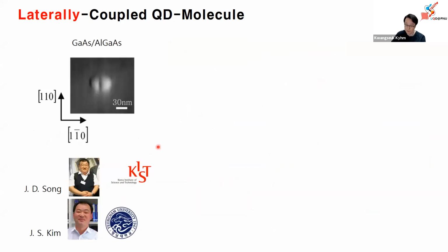However, our approach is a bit different. We use a laterally coupled quantum dot structure, and the samples were grown by our collaborators. Those two people are experts in droplet epitaxy, and this is our sample. It's gallium arsenide, very clean, capped by aluminum gallium arsenide, with two droplets separated in the middle. The distance between the two tops is roughly 30 nanometers, so in this case tunneling is very unlikely.